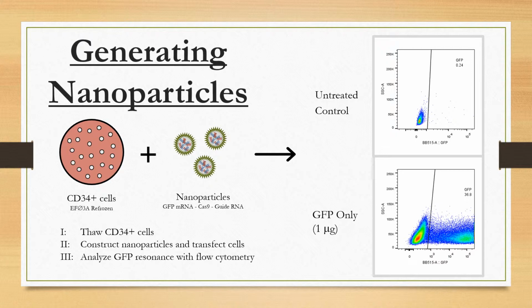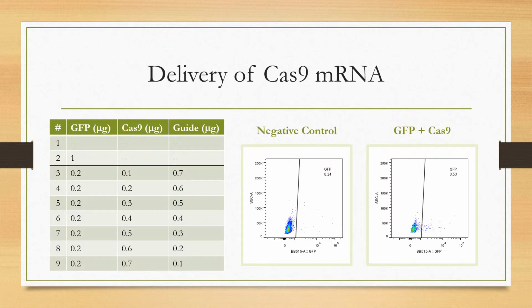On day 3, we harvest our transfected cells and analyze them with flow cytometry, with adequate GFP fluorescence affirming that the nanoparticles were taken up by the cells. When using Cas9 mRNA, we use an untreated cell sample and GFP-treated cell sample as our controls. For the nanoparticle-treated sample, we varied the Cas9 guide ratio between each of the samples in order to test which titrate ratio maximized the efficiency of the nanoparticles. According to the results of the flow cytometry, it appears that in each sample, the cells were successfully transfected with the nanoparticles.